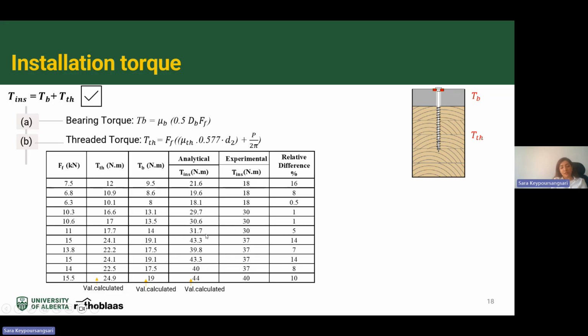We compared our result with the experimental one, and you can see there is a good agreement. The maximum relative difference in one case was around 16%. The reason we did that is because we want to find the stress on self-tapping screws, and we need to know about the threaded torque.